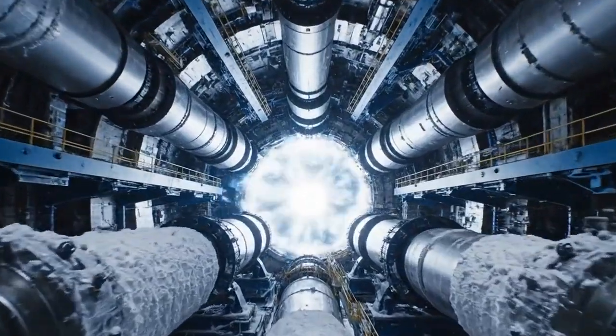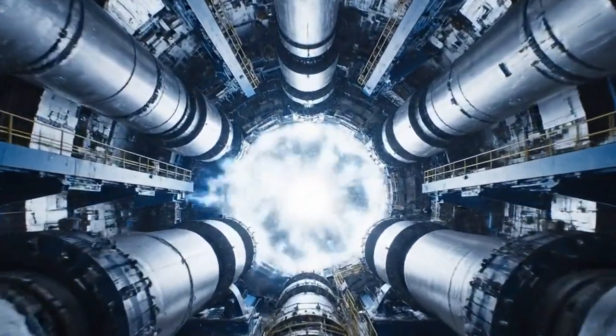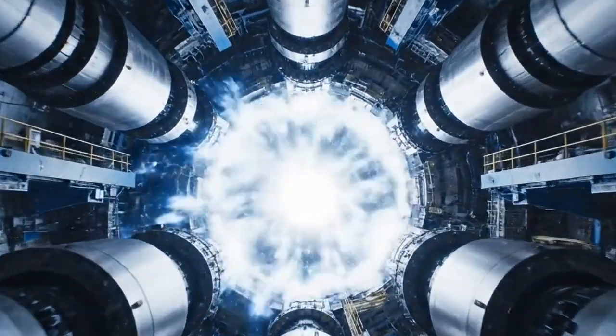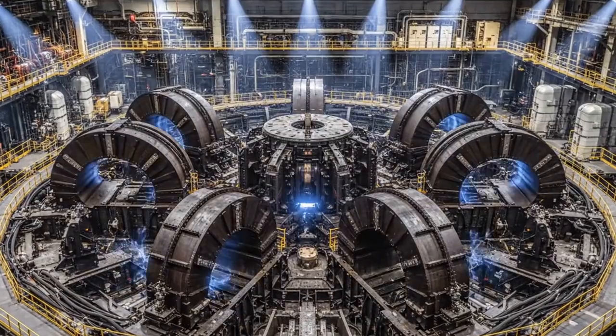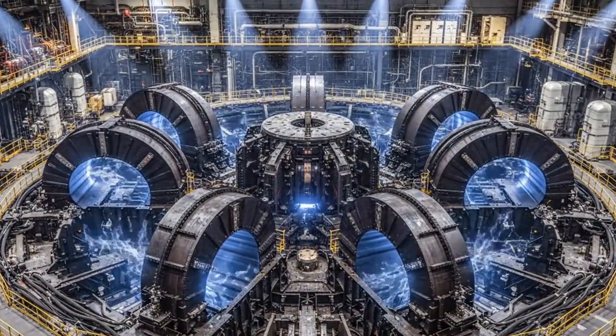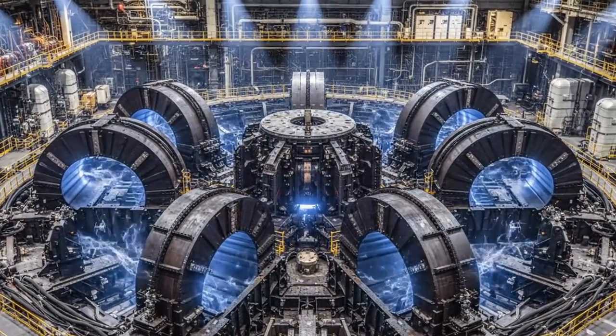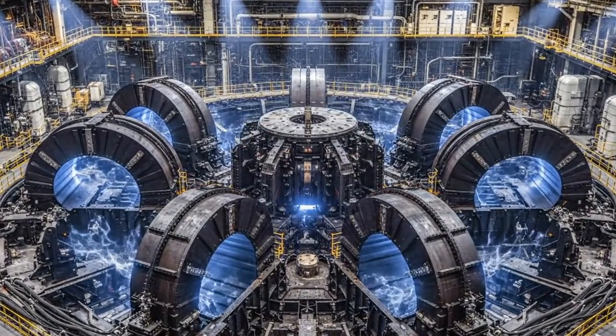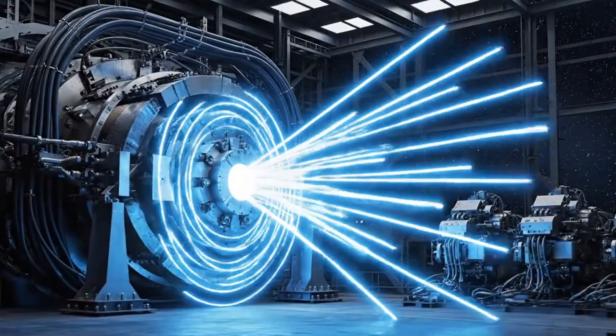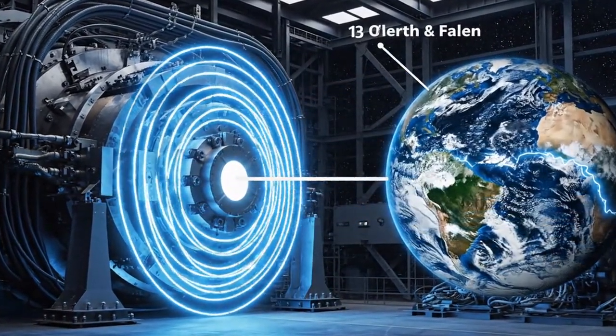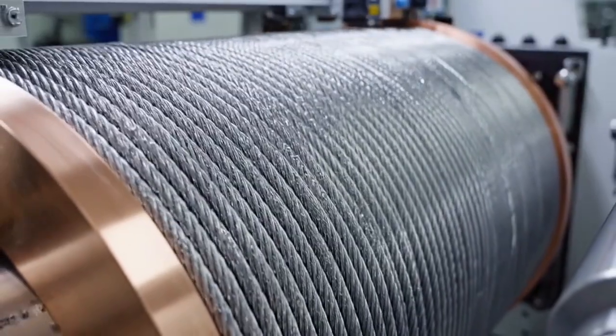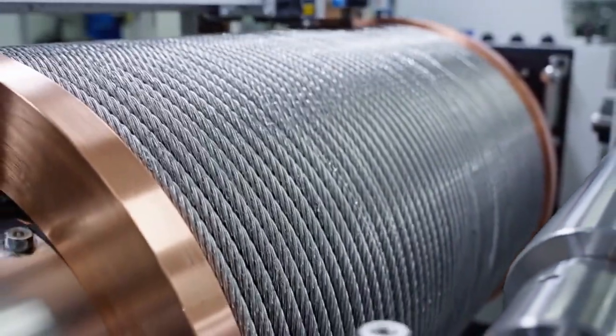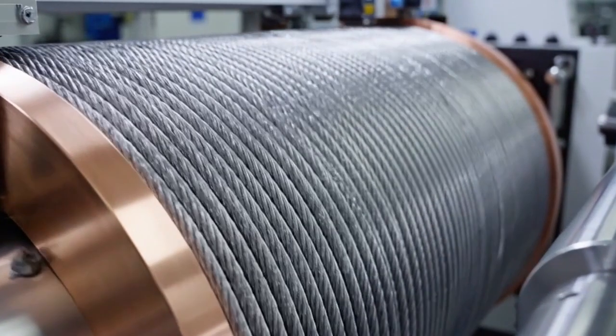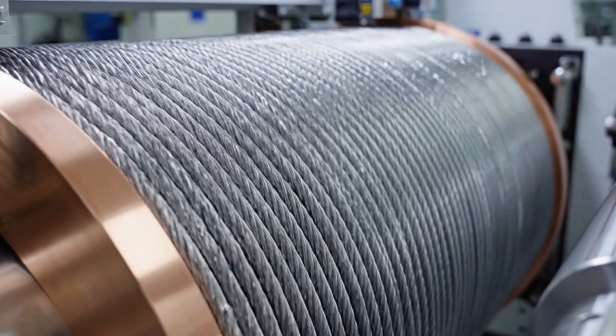To trap the volatile 150 million degree plasma, the reactor relies on a complex array of superconducting magnets, including 18 toroidal field coils, 6 poloidal field coils, and a central solenoid capable of inducing a peak magnetic field of 13 Tesla. This is roughly 280,000 times stronger than the Earth's natural magnetic field. These coils are wound from over 100,000 kilometers of specialized superconducting strands, primarily utilizing niobium-tin and niobium-titanium alloys.